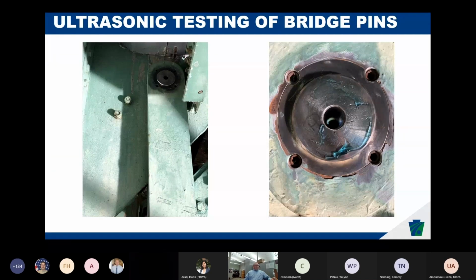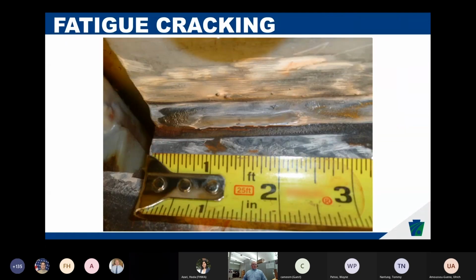And then I think most states still have a significant number of pin and hanger assemblies and truss bridges that use pins. So we routinely inspect those for any type of wear damage. We have now allowed, in some special provisions on maintenance contracts, the use of phased array ultrasonic testing to inspect these pins, which gives you a little bit better view and a permanent record for doing some type of condition monitoring, and fatigue cracking.